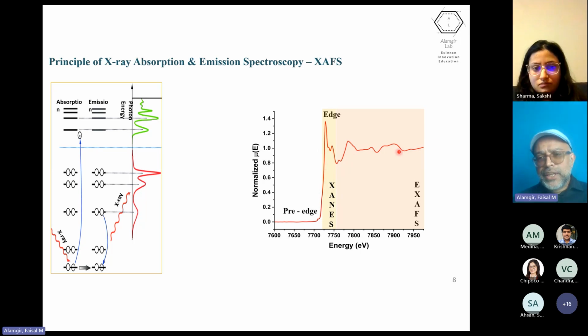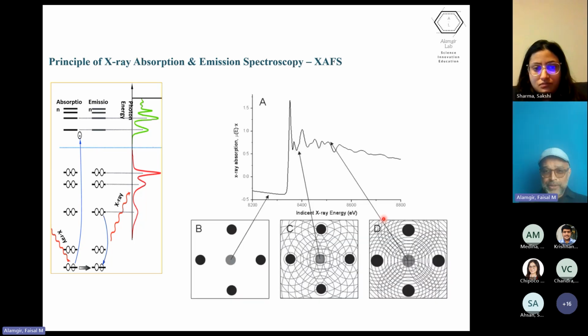And then the extended region here, the so-called EXAFS, is giving you the local atomic structure. So let's look at that EXAFS part a bit closely. Why do we even have that? To say it simply, we have it because the electron, once it's released and once it's past the conduction band and is within the vacuum of the atom of the material, is now a free electron wave.